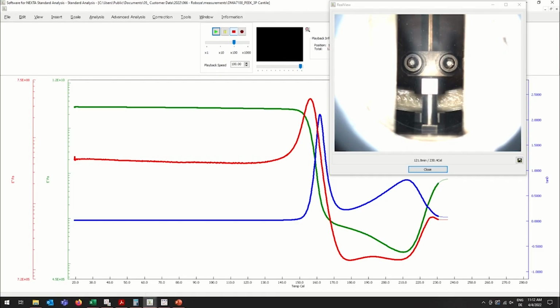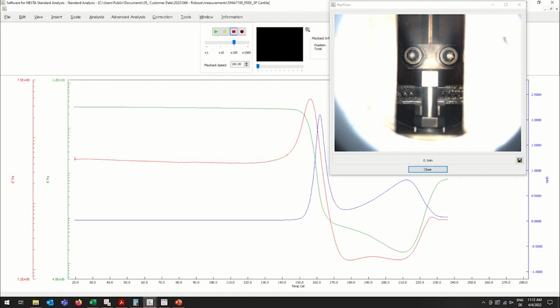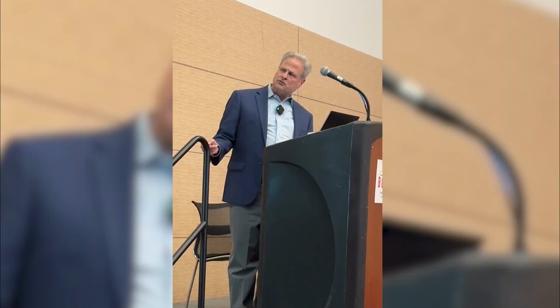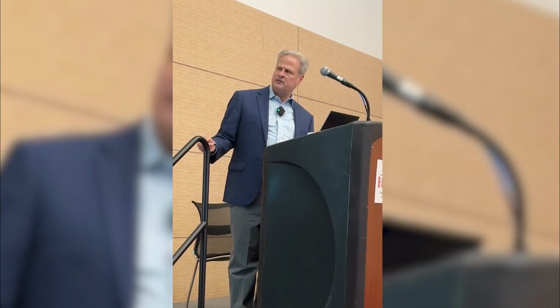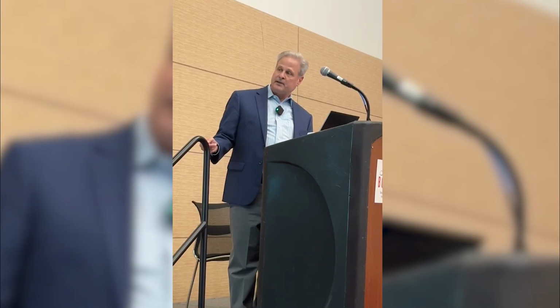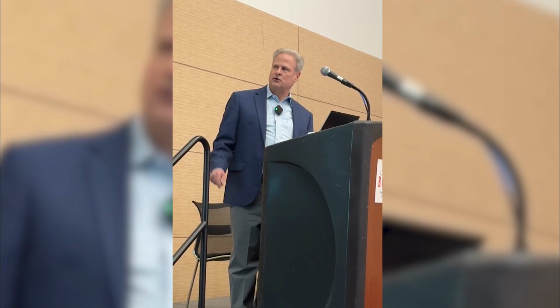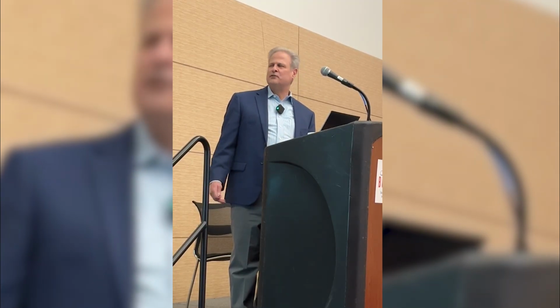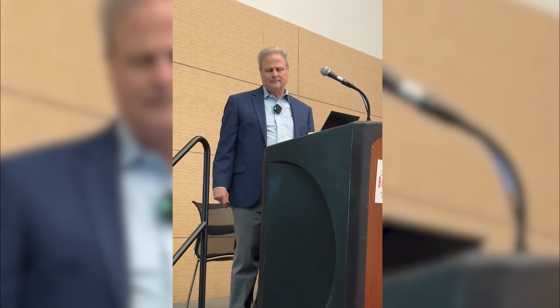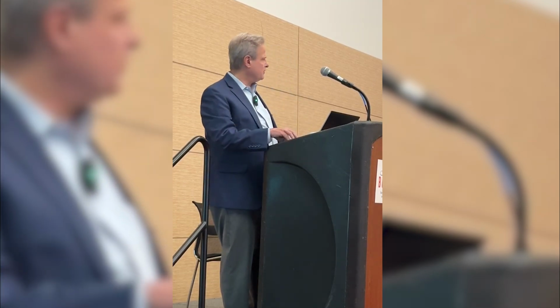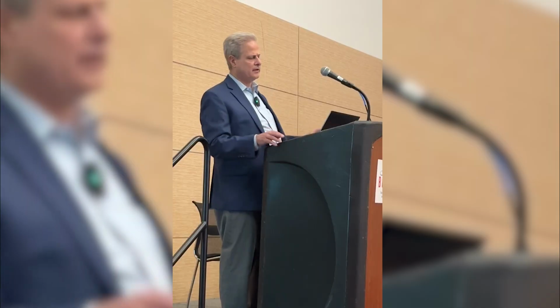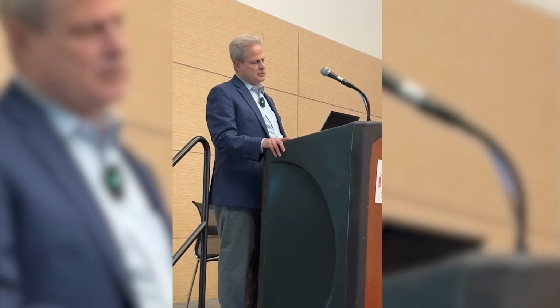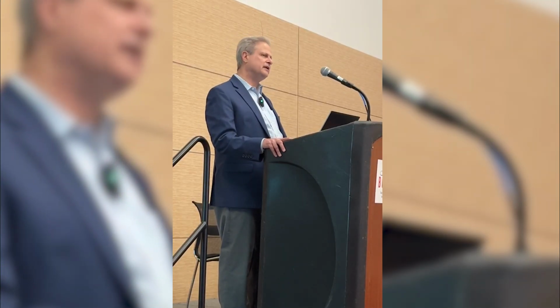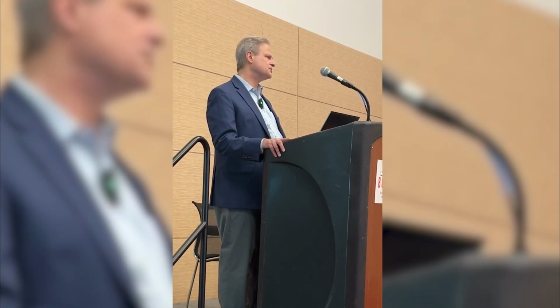The sample became crystalline. I don't know if you observed that, but it was more translucent. When we go through the Tg, there's enough molecular mobility to crystallize. It became opaque, and then it started to melt again. So that's an example of DMA. Quite frankly, I would say probably the DMA is more artifact related. I think there's more information in DSC and TGA, would be my guess.